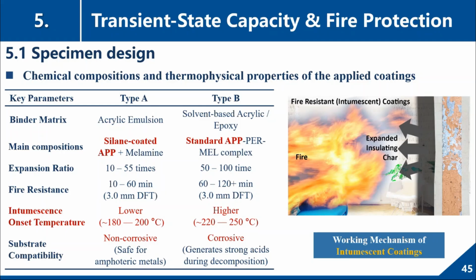So we need a new intumescent coating with a lower onset temperature. This is the first one. The second one is that the ordinary coating for steel structure is corrosive, but the new one is non-corrosive. So we call the new one type A and the ordinary one type B. And we use these two kinds of coatings on our cross sections, stub column members, and then we put them into the furnace to see what's the difference of these two coatings.